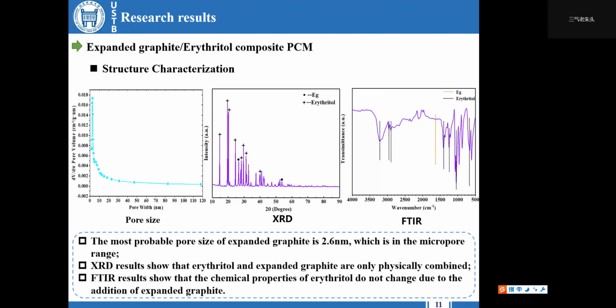Then the structure of the composite material was characterized, and the most probable pore diameter of the expanded graphite was 2.6 nanometers through nitrogen adsorption and desorption experiments, which belongs to the range of micropores. From the XRD results, characteristic peaks of erythritol and expanded graphite can be seen, and no new characteristic peaks appear, indicating only physical bonding. The FTIR results show that the chemical structure of erythritol didn't change after the addition of expanded graphite, further proving that there was no chemical reaction between the materials.